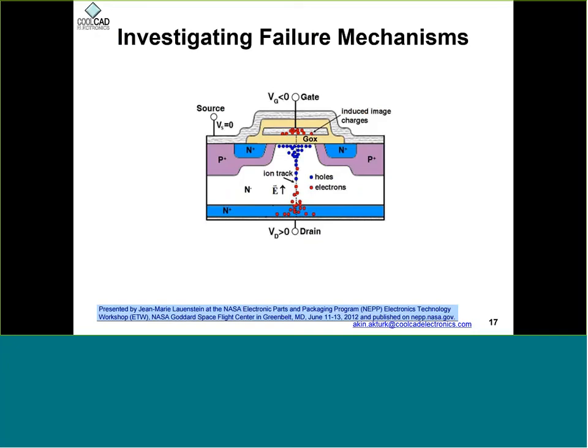This is similar to heavy ion induced power device failures, and these tests are done for space applications as well. That failure can be in the form of a burnout or a gate rupture. In the burnout case, you have a current flowing between the source and drain, and that's sustained for long enough, and in the meantime you have lots of Joule heating within a very small area, which then causes lattice damage and shorts source and drain.